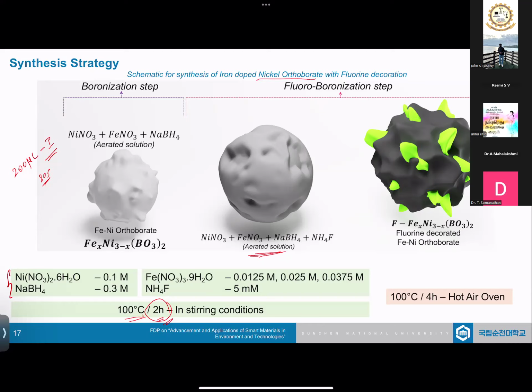Now, what did we do is, we know that iron has a very huge role in terms of oxygen evolution and hydrogen evolution. But we also know that there is a certain percentage after which iron will inhibit the activity completely. So what did we do? We went on 3 different concentrations, and we tried to evaluate the material, and we found out that the lowest concentration was the best possible option. And we had the iron doped nickel orthoborate, where the iron is replacing the nickel atoms, and we get still a stable system, which I'll show you in the later half.